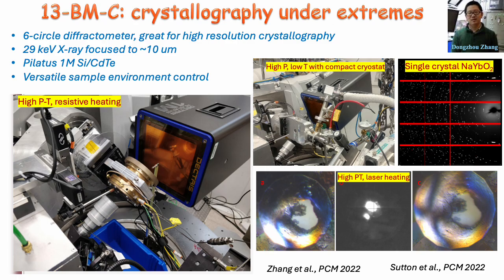As I have mentioned, 13 BMC is dedicated to high resolution crystallography using a 6-circle diffractometer. The energy at 29 keV allows us to have high resolution diffraction with a reasonably small beam size around 10 micron. We can use a silicon cadmium telluride detector, and we can change different environmental conditions for the sample. As you can see in this picture, we can run an external heated cell, and we have an observation optical system to see the sample, as well as do simple Raman and one-side laser heating.